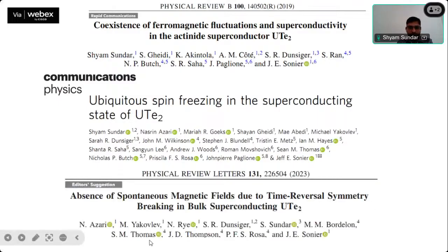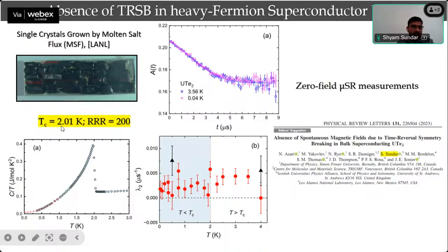So we got another very good quality crystal which shows slightly larger Tc, because the initial superconductor of uranium ditelluride showed the Tc around 1.6 Kelvin, but this is a better quality crystal, which has RRR, the residual resistivity ratio, of 200, and it shows a Tc of around 2.01 Kelvin. So when we did the same zero field measurement, we did not see any magnetic relaxation as a function of time. So we can confirm from this measurement that this superconductor does not show any time reversal symmetry breaking. This tells a lot about the superconducting behavior in this uranium ditelluride superconductor.